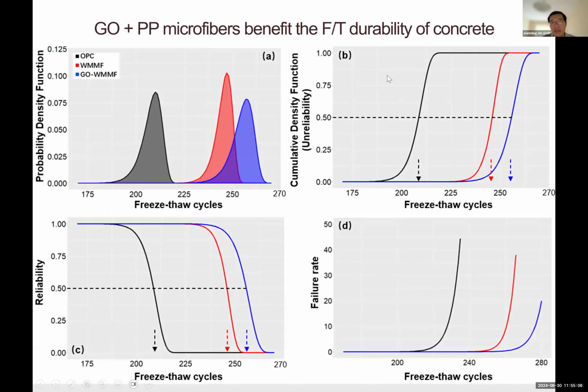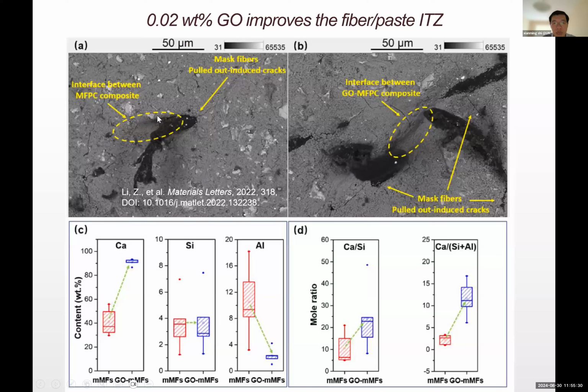And we translate that to stochastic modeling. So again, the blue curve shows it can endure a significantly greater number of freeze-thaw cycles compared with the ordinary Portland cement, or compared with just the mask fiber without the GO treatment. I won't go too much into these details, but we also look at why it happens. Again, you see some sort of fiber pullout, consuming some of the fracture energy.